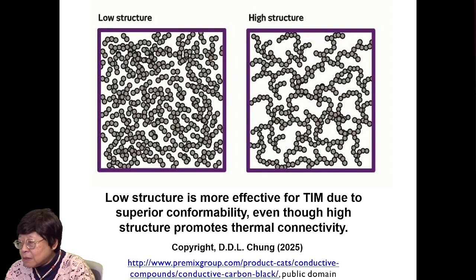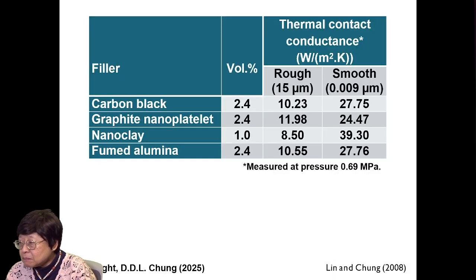Now, there is low structure carbon black and high structure carbon black. Low structure means the aggregate size is smaller. Low structure is more effective for TIM due to the superior conformability, even though the high structure promotes the thermal connectivity.